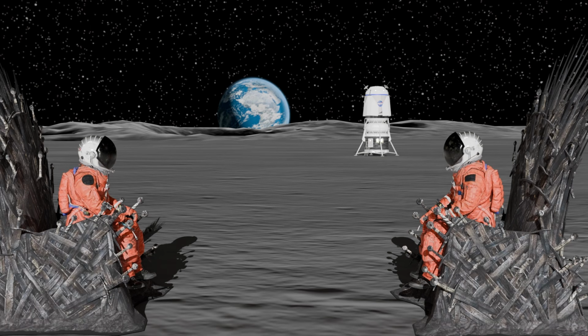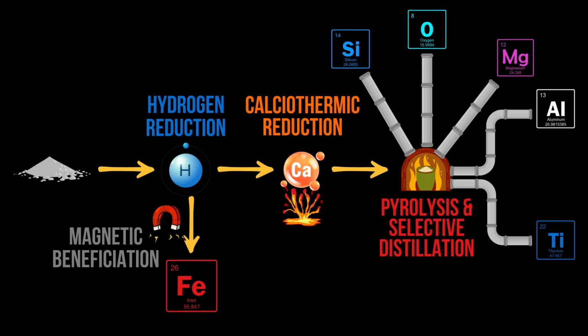So I'm imagining that the step-by-step industrial process might be something like: first you gather regolith, then you do hydrogen reduction and pull out the iron with a magnet, and then you would maybe do calcium reduction, so you're left with an alloy cake that you could put through the pyrolysis process, and you'd be able to sublimate those metals at much lower temperatures. And then you obviously need to return your calcium oxide.